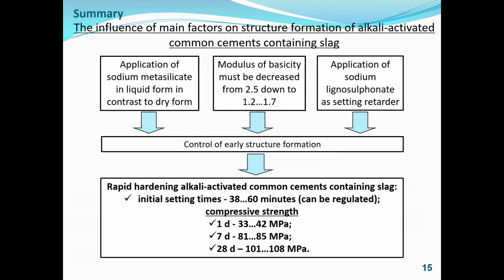Thus, it was revealed that alkaline activation with the help of sodium metasilicate in liquid form, in contrast to dry form, while necessarily decreasing the modulus of basicity from 2.5 down to 1.2, 1.7, as well as application of sodium lignosulfonate, a setting retarder, allows control of early structure formation. This resulted in obtaining quick hardening alkali-activated common cements containing slag with regulated initial setting times of 38, 60 minutes and high strength gain similar to that of high alumina content cement.